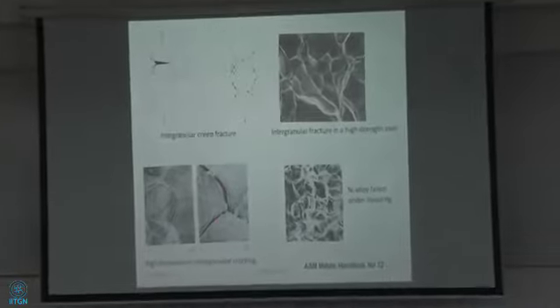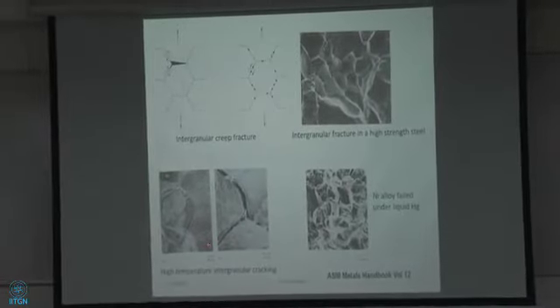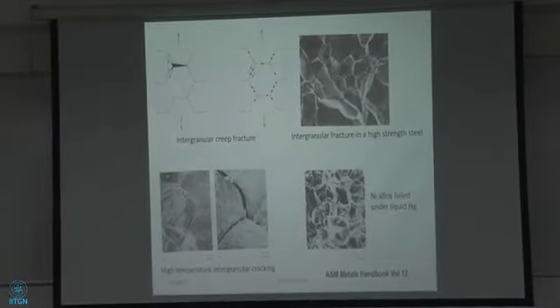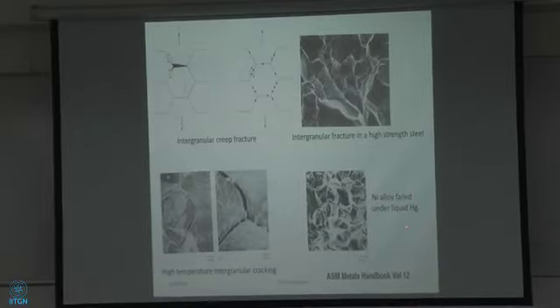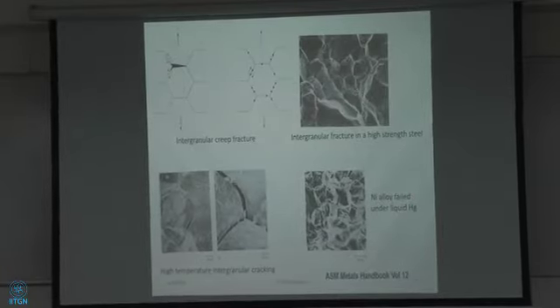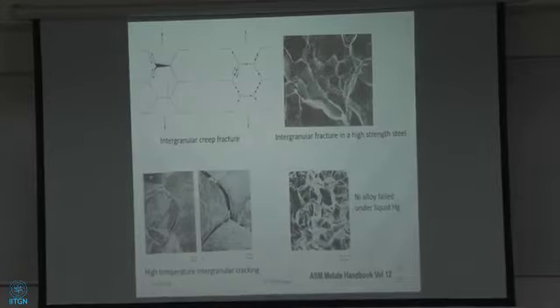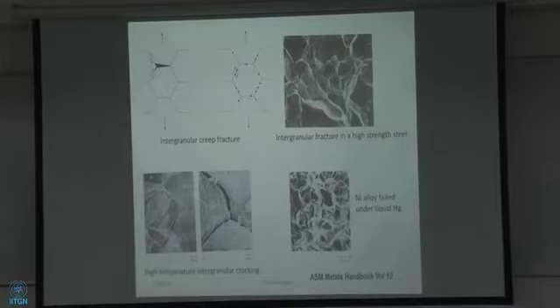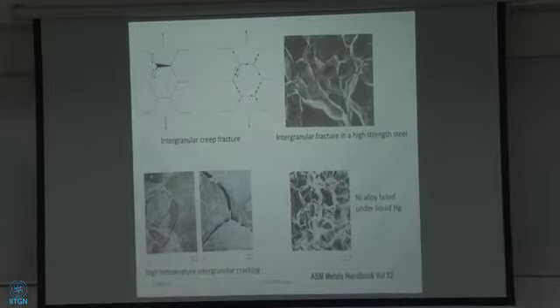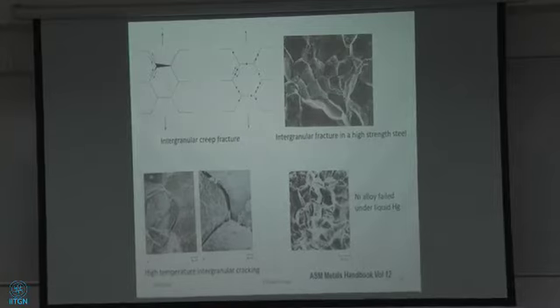High temperature intergranular cracking. Okay. Nickel alloy failed under liquid mercury, for instance. This is what I was talking about. Like, for instance, mica crystals with water. The same way nickel can fail if you put it in liquid mercury, it'll fracture by intergranular fracture really easy. Okay? Very easily. Intergranular fracture in high strength steel. Okay.